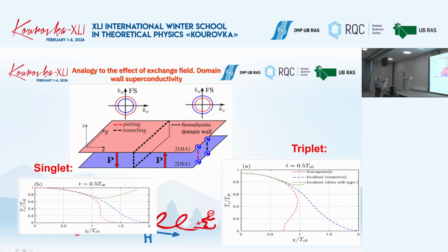Look, these blue curves, for singlet and triplet pairings, show you the behavior of the critical temperature for this domain wall superconductivity. At this point, I must say that if we turn to the analogy with ferromagnetic domain walls in superconductors, exactly this problem was solved many years ago by Bulaevskii, Buzdin, and other authors. The difference here is that to model these structures, we included the tunneling between the layers, so it's different in this sense. But of course, the ideology is very close.